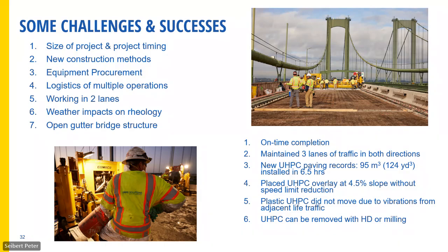And then I don't think we have any slides on it, but there was a truck fire on this bridge right on top of the UHPC that we'd put in on a previous phase. So we wound up having to go in and do an emergency repair. The emergency repair was done by a milling operation and then just a small application of UHPC with a small screed. And then we went back the following season and removed that entire section from joint to joint using hydrodemolition and replacing that entire overlay through there. So we found that small repairs can be done more easily than we thought. Larger removals and reapplications can be done way more easily than we thought. So it was a great learning process and understanding what can be done.